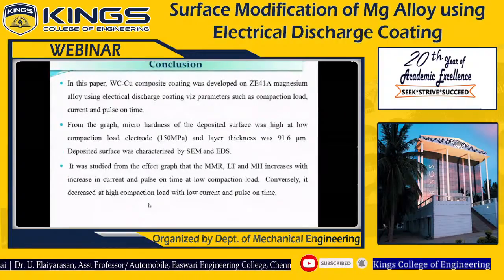So coming finally to the conclusion. In this paper presentation, tungsten carbide copper composite coating was developed very successfully using electrical discharge coating on the ZE41 magnesium alloy. Different parameters have been studied, and from the microstructure graph, several features like globules, craters, and cracks were formed. The highest coating thickness, 91.6 micrometers, has been achieved in this study.